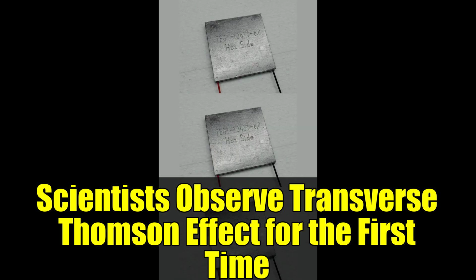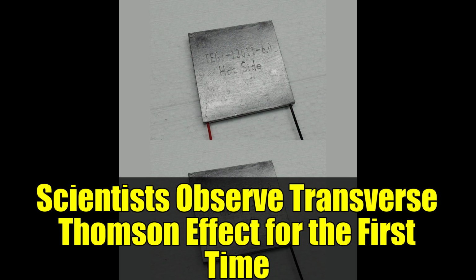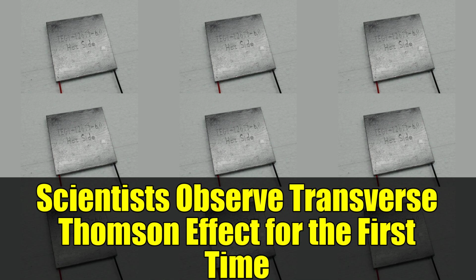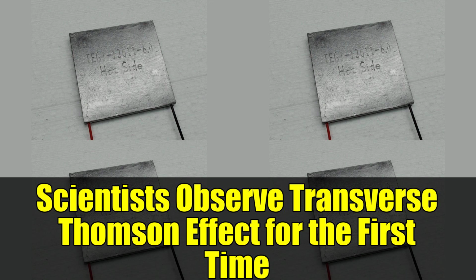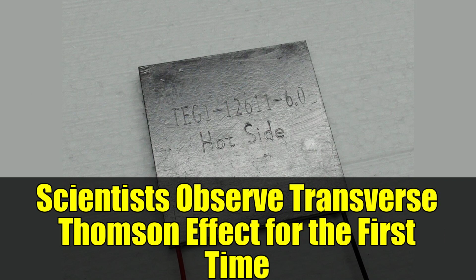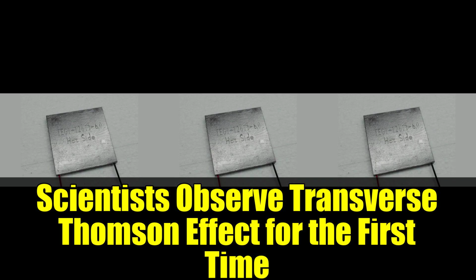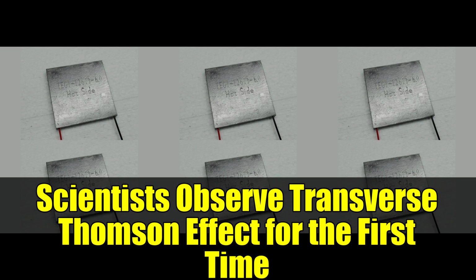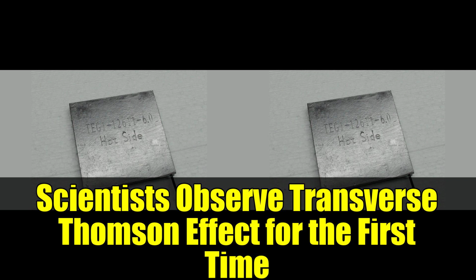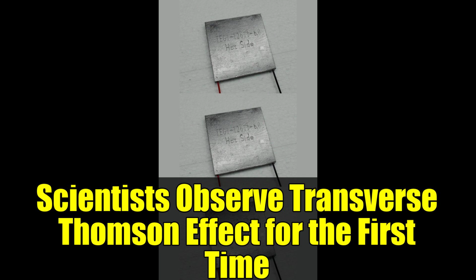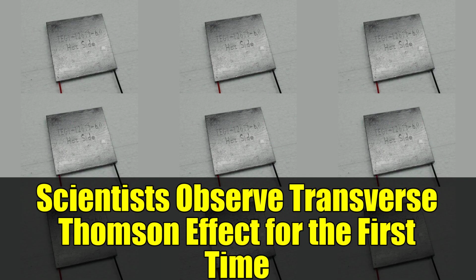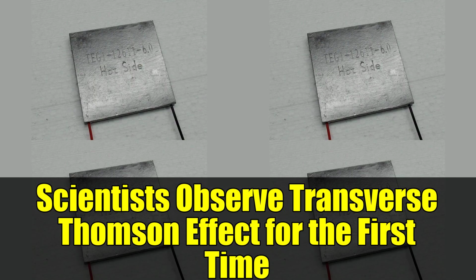Our research revealed that the magnitude of the heat source responsible for the Transverse Thomson effect is determined by both the temperature derivative of the Nernst coefficient and the Nernst coefficient itself, Takahagi explained. The Bi88Sb12 alloy, with its large Nernst coefficient, proved to be an ideal candidate for exhibiting the Transverse Thomson effect. This is a fundamental difference from the conventional Thomson effect, which depends solely on the temperature derivative of the Seebeck coefficient. One of the most surprising discoveries was the ability to switch between heating and cooling by simply changing the magnetic field direction. The effect showed complex field-dependent behavior, including a complete sign reversal at certain magnetic field strengths.